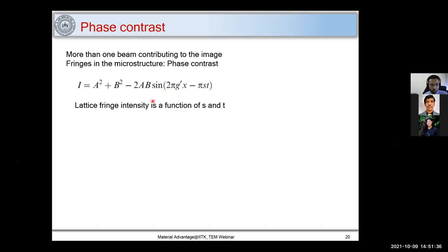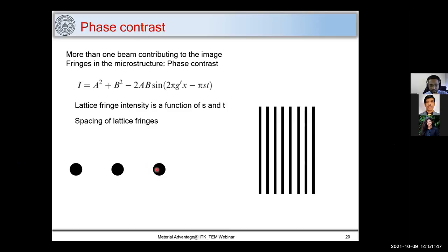So let's understand how these lattice fringes form when I talk about phase contrast. Let's consider these 3 diffraction spots. When I consider this, I will get fringes in this pattern. So when I'm considering these 3 spots, these fringes are perpendicular to this direction. Let us mark that. Here I can consider this as G, which is a reciprocal lattice vector, and it will be given as 1 upon D, which is nothing but the fringe distance. So this distance is D, and this distance will be 1 upon D. So it is inversely proportional to the D spacing of these fringes.